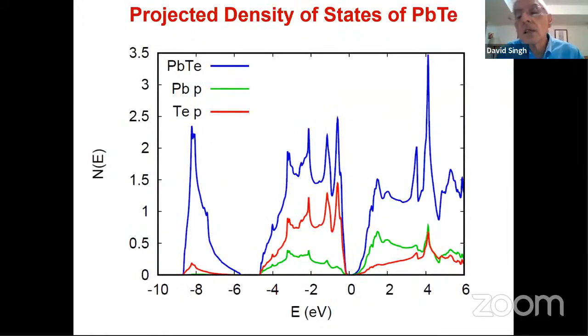So we see exactly the same thing in lead telluride. And what does good semiconducting behavior mean? It means weak scattering of the electrons that gives high conductivity. And we see the same thing in lead telluride. So lead telluride, this is just showing the electronic density of states and showing that even though it's lead 2+, there's quite a lot of lead character occupied. And even though it's tellurium 2-, there's quite a lot of unoccupied tellurium character due to this kind of hybridization that I mentioned before.